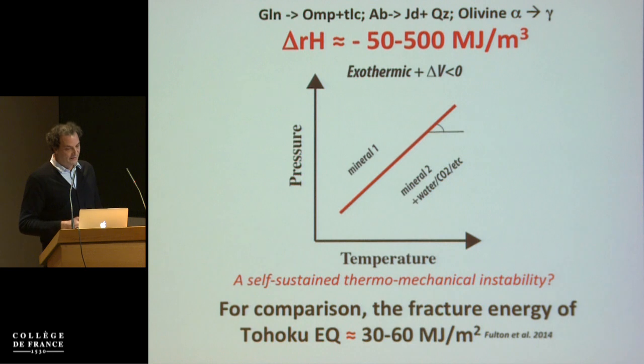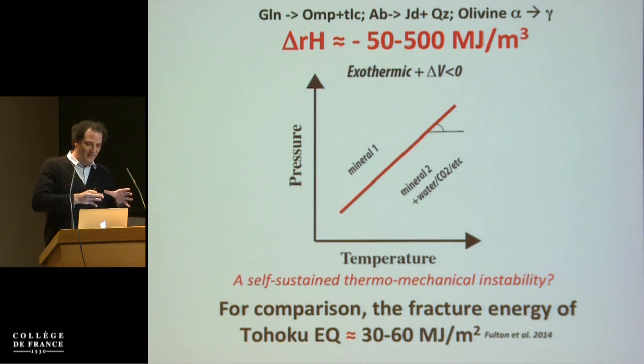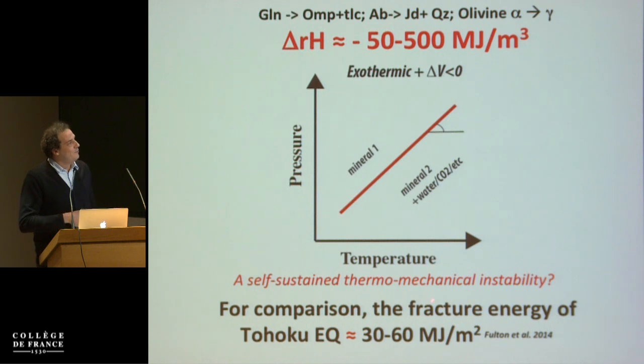because obviously it's not a nil process. And just for you to see, in the case of the olivine alpha to gamma transformation, it's exothermic, and the latent heat is around half a gigajoule per cubic meter. So if you transform 1 cubic meter of olivine into its gamma phase, it will produce half a gigajoule of heat. And the fracture energy of the Tohoku earthquake is around 30 to 60 megajoules per square meter. So basically, in 10 centimeters of olivine transforming into spinel, there is as much heat as in 1 square meter of Japan sliding 50 meters. Okay, so just to tell you that those energies are not to be neglected.